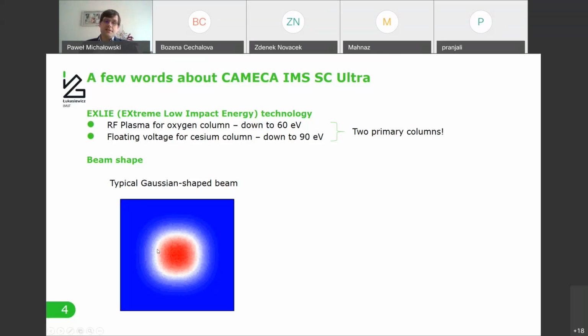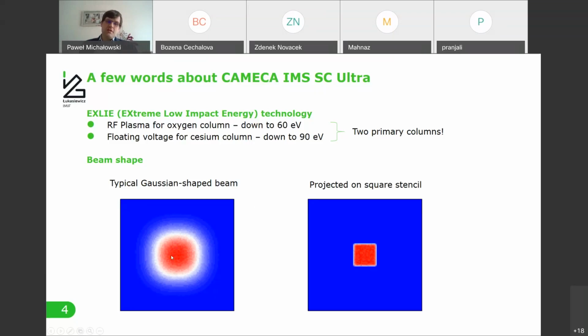So in here, CAMECA is still generating the very same Gaussian-shaped beam, but then is projecting it onto square stencils made of tungsten, so that we choose only the middle part of the Gaussian beam, the most intense and most homogeneous part. So in the end, what is hitting the sample is a rectangular beam with still quite high intensity and very homogeneous. And if you think of it, such a beam can really sputter the material homogeneously, so you can really expect the sputtering process to be layer by layer. So with these two combinations, it can increase the depth resolution significantly to values well below 1 nanometer.